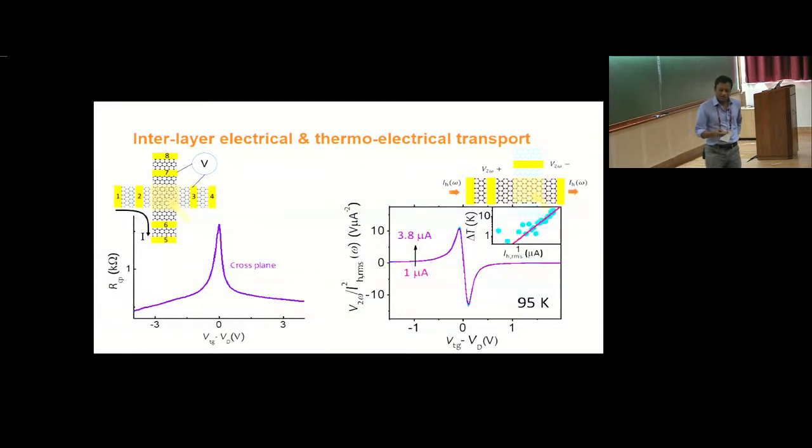That's an excellent question. Actually, we have seen exactly that. You go to higher harmonics and you divide by that power of current and you will end up getting a collapse. So most of it, I would say, we look at the other features of thermoelectrics. We see the Mott formula, whether they agree or not, and also try to keep the heating geometry as well defined as possible. There's one unique aspect here, that we always use graphene as the contact rather than metal directly, where the contact effect can probably be significantly reduced. But we have seen this effect, and we are aware of it at least.